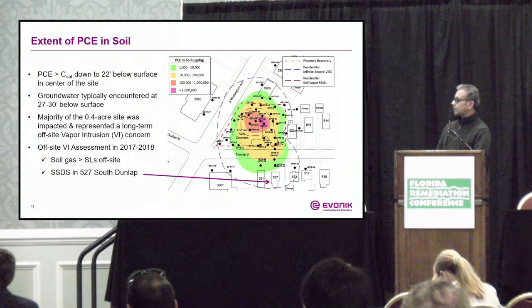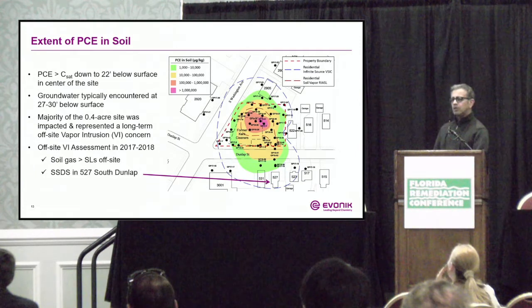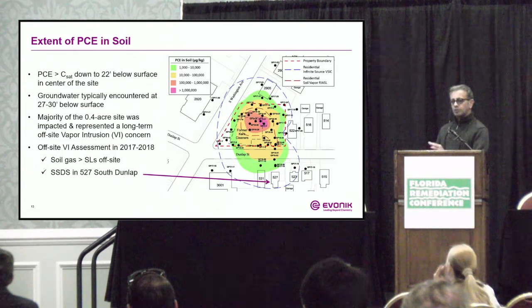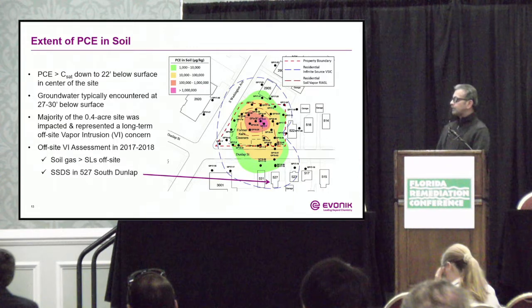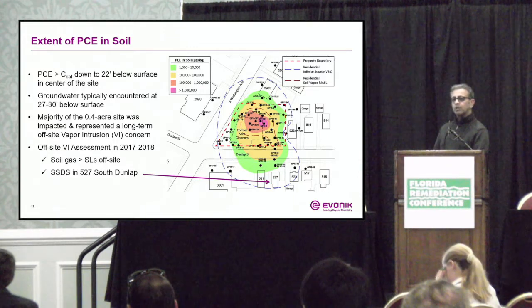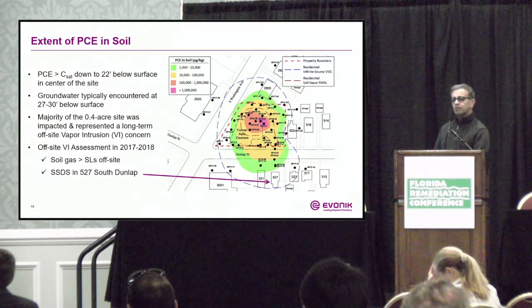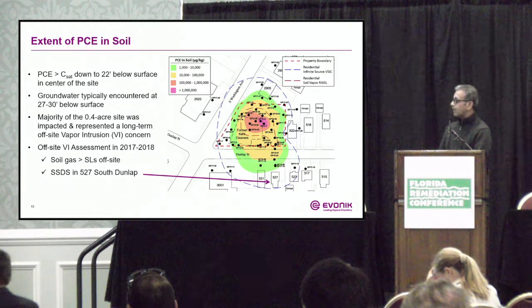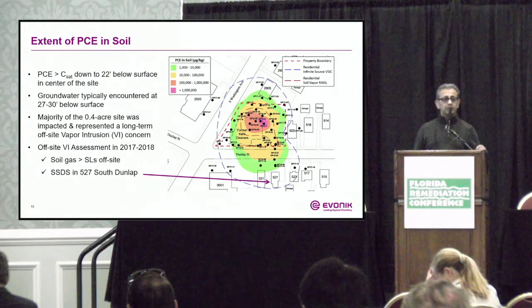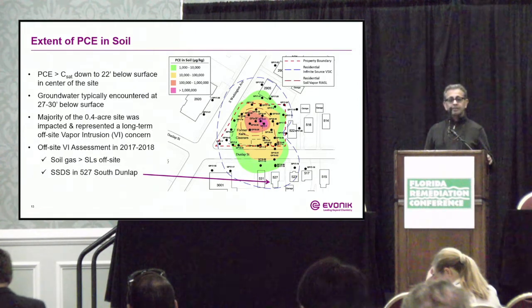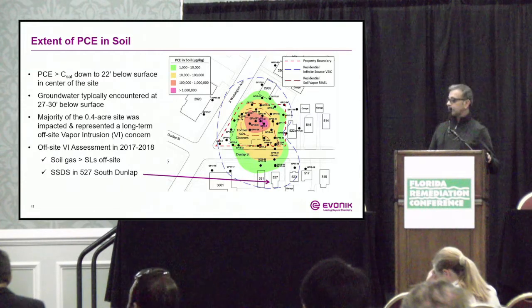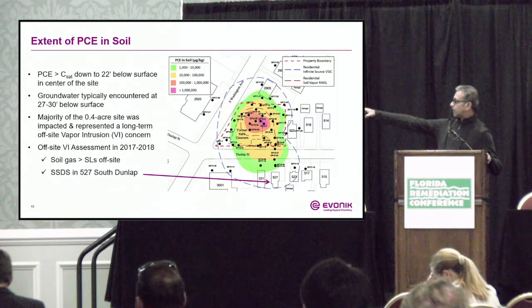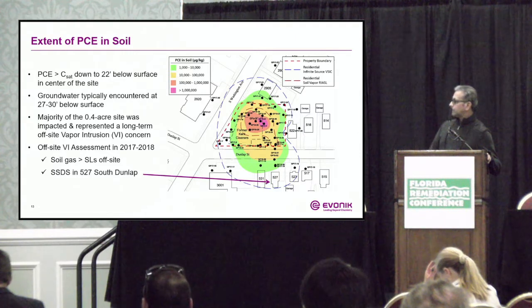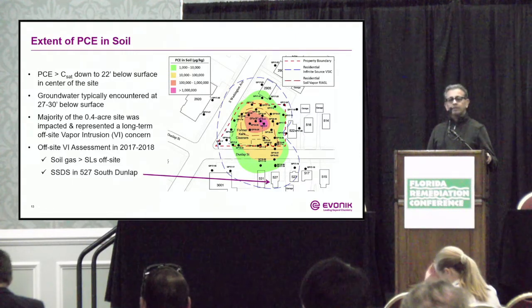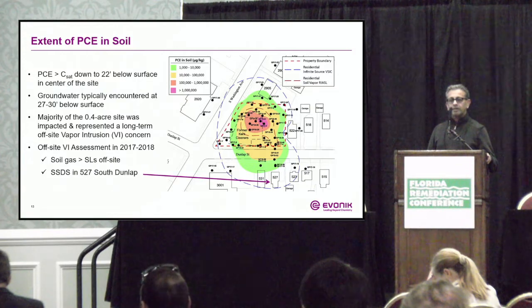The groundwater is about 27 to 30 feet below ground surface, so this was mostly an unsaturated soil contamination problem that posed a significant vapor intrusion problem. An off-site investigation was done for VI in 2017 and 2018, and they found significant concentrations detected above standards in some of the residential houses at the bottom. And then one of the houses, as you can see there, at 527 South Dunlap, they had to install an SSDS system to mitigate the vapor intrusion.